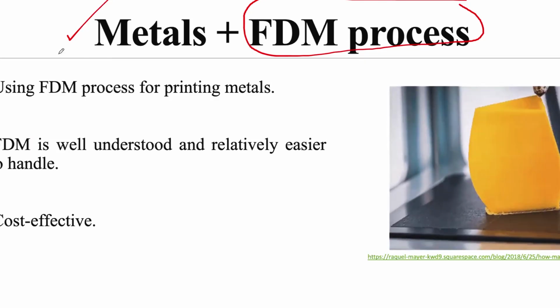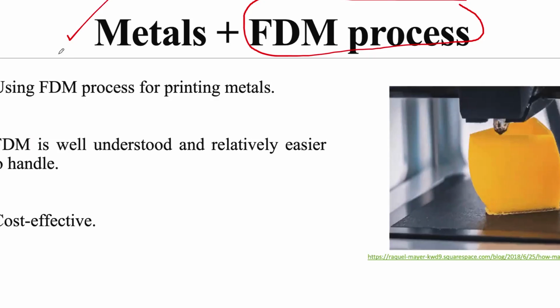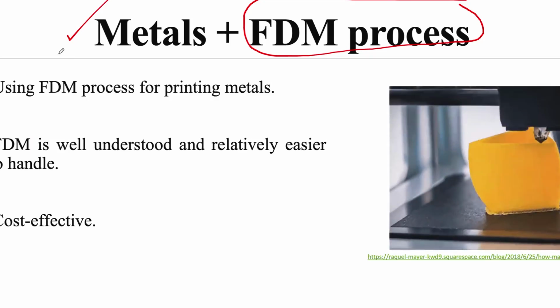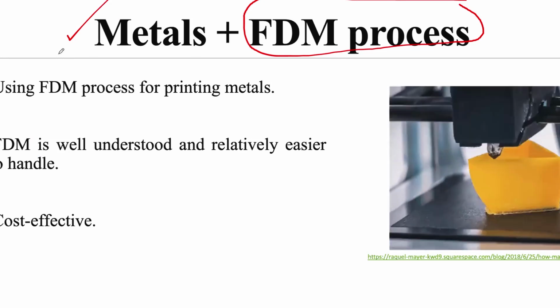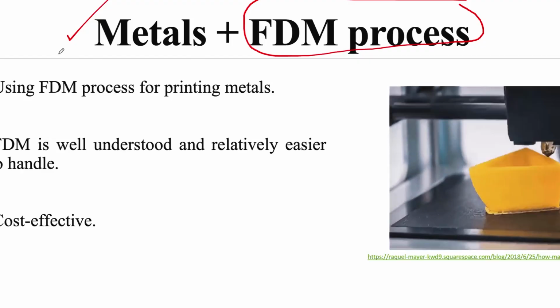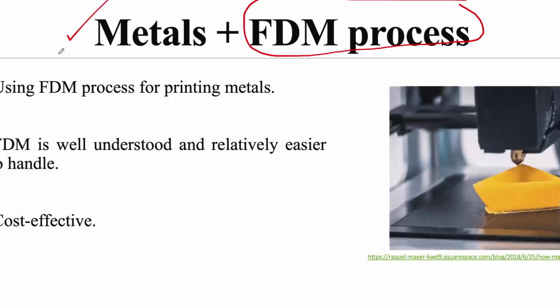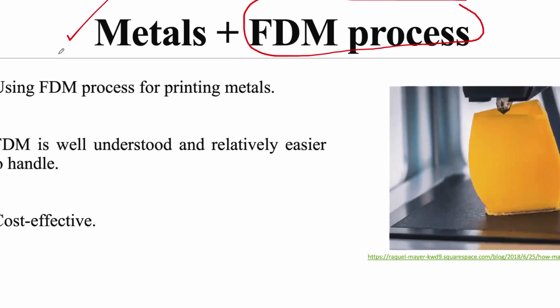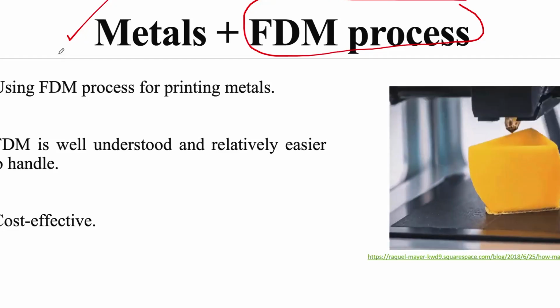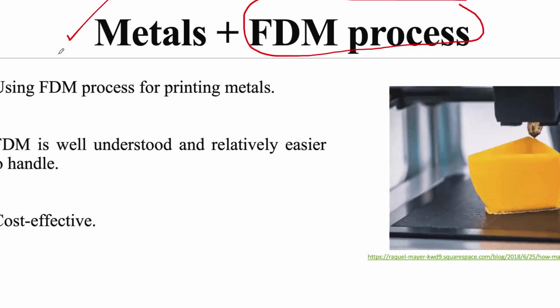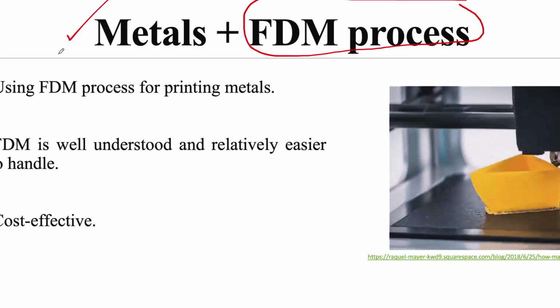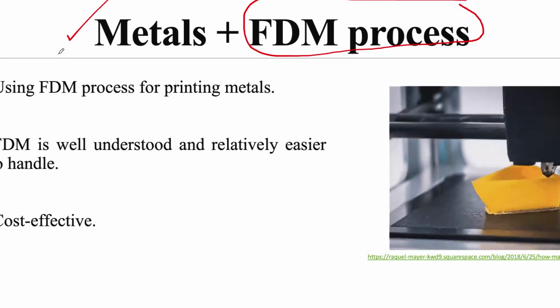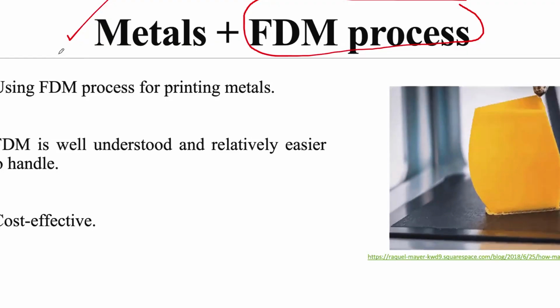Because if we understand how we can modify our existing printers for 3D printing metals, it not only solves the problem of lightweightedness, but it will also solve the problem of cost. It will bring down the cost significantly. Just to give you some numbers, if you want to buy a laser-based 3D printer, an SLM setup, that setup will easily cost you around 1.5 crore. The cheapest one will cost 1.5 crore to 2.5 crore, and a good one might cost around 3 to 4 crore, 5 crore, or even higher. Another constraint in these kinds of setups is that if you have to print a very small part in metal, you have to fill the setup with at least 8 to 10 kilograms of powder.